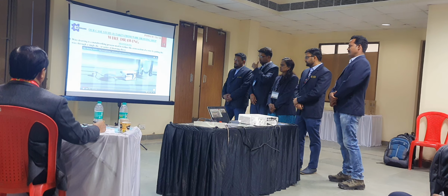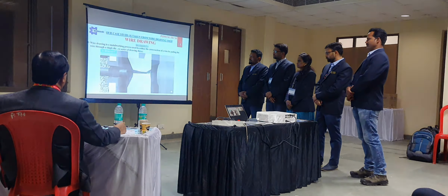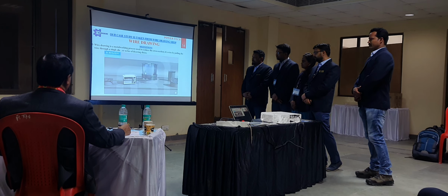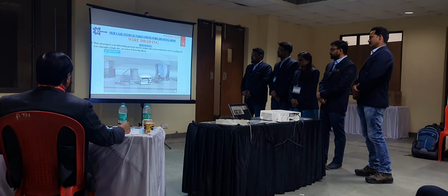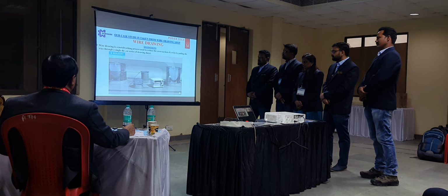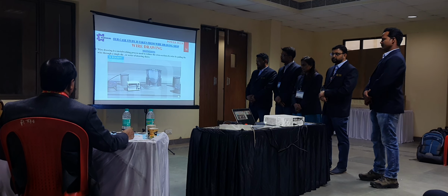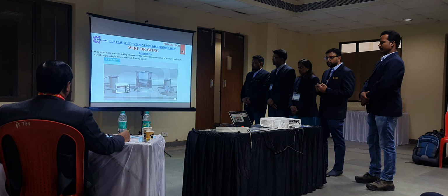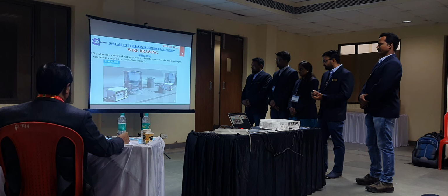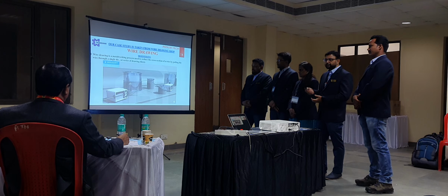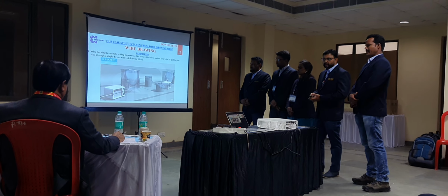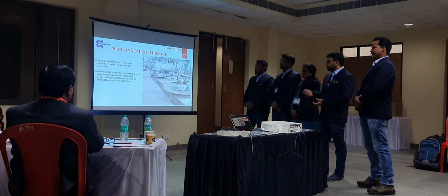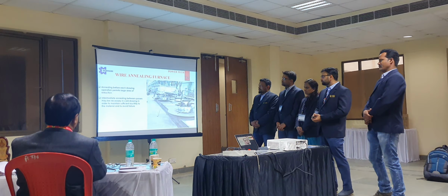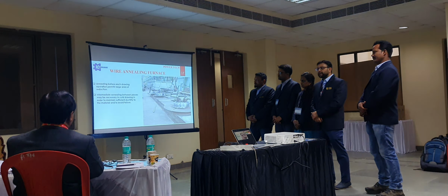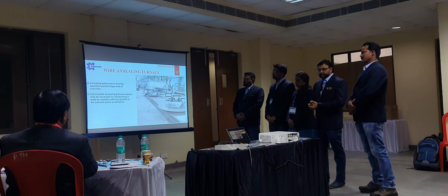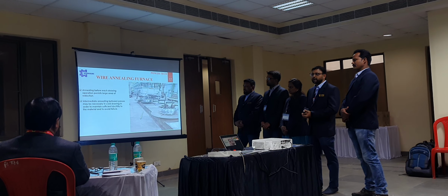Through the animation we can see that after lubricating, the wire passes through the die where the cross section gets reduced and is sent for further reduction. This is a continuous process, and after a certain stage the wire tensile strength becomes so high that the ductility of the wire will be low and the chances of wire breakage will be high. So we have to stop the process here and send the wire for annealing for further elongation. Annealing is a process to reduce the material work hardening and to make the wire more ductile for reduction purposes and to ease the wire drawing process.